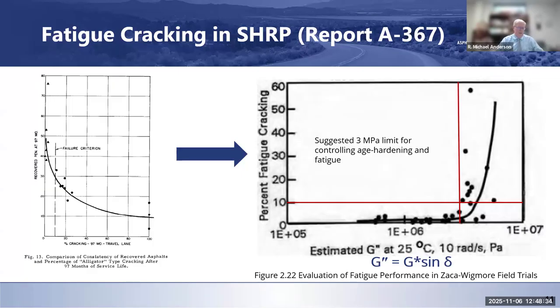And I think that was one of the nice things about M332, which uses MSCR, is the understanding that for many of us, we're not living in climates that are 76s, but we're still using 76-22s. Kentucky, for example, where I live, on an interstate, a PG 76-22 is common. It doesn't get anywhere near as hot as 76 degrees in Kentucky, but that's what the binder is that we're calling for. If you're using M332, that becomes a 64E, and that changes what your intermediate temperature is. And so that's the way we mitigate what some of that looks like, I think. Hopefully that answered the question. That may have been a long-winded response to not what you were asking.